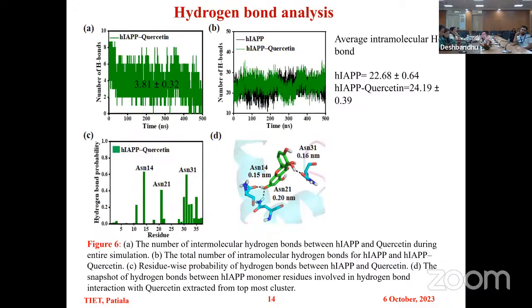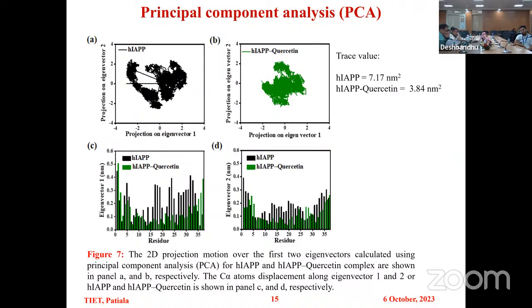Further, we performed hydrogen bond analysis, and from it we got a very good number of H bonds between HIAPP and quercetin. The intramolecular H bonds were also found to increase, which shows the stability. These are the residues which were involved in the hydrogen bond formation. Next, we performed the principal component analysis, and from the PCA analysis, we can clearly see that trace values were decreased in presence of quercetin, which shows that conformational motions of our protein were restricted in presence of quercetin.